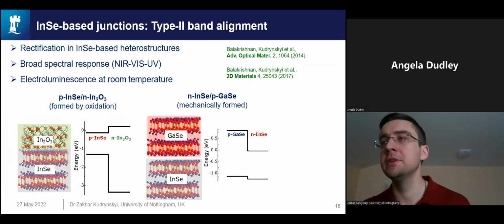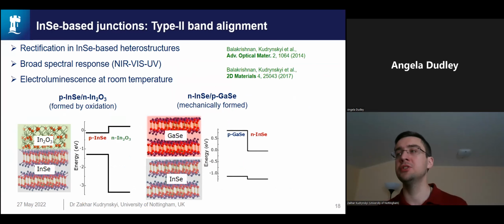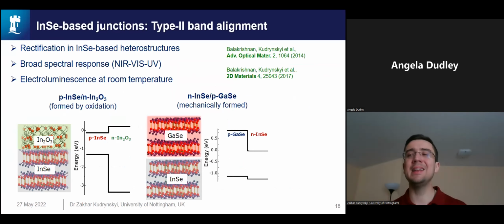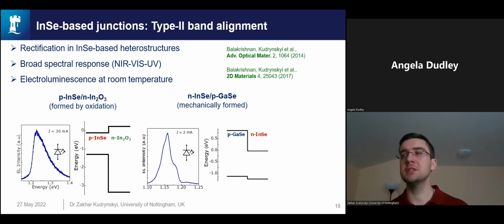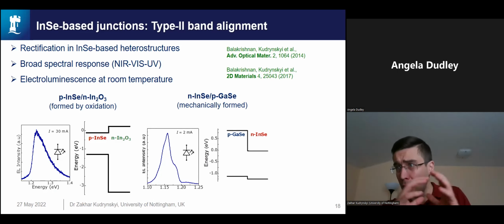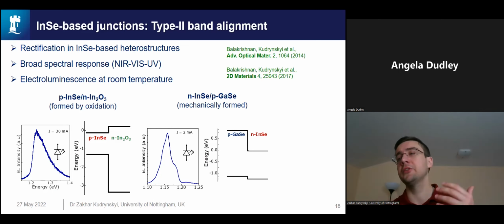We have also developed and fabricated a number of PN junctions with type 2 band alignment, combining indium selenide with other materials. For example, heterostructures produced by controlled oxidation of indium selenide to form P-type indium selenide and N-type indium oxide junctions, or mechanically by a dry transfer of flakes of other van der Waals crystals on indium selenide, for example, gallium selenide. And these p-n junctions have a number of useful functional properties, such as rectifying behavior, broad photoresponse in zero bias, and electroluminescence at room temperature.